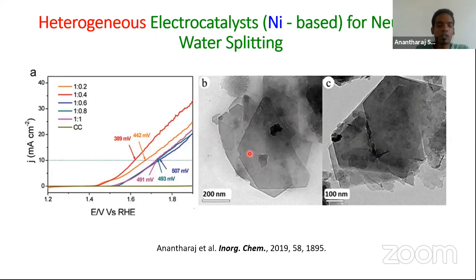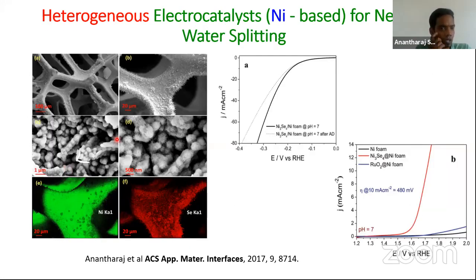layered double hydroxide material. But in this case, we applied this material for neutral water splitting, where we obtained a very low overpotential. I mean, this is the lowest so far as far as neutral water splitting is concerned for 10 milliampere current density. And we also showed nickel selenide, which does not have any common ion with that of the electrolyte. I mean, the electrolyte used here is PBS, and the electrocatalyst is nickel selenide. Even then, we obtained very good activity for hydrogen evolution reaction and oxygen evolution reaction.